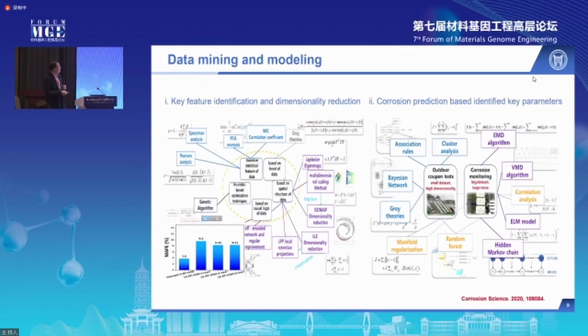And for data mining and modeling, because corrosion is a complex term and it's affected by a lot of different factors, we believe that corrosion data is of high dimensionality. So we applied a two-step approach for data analysis. The first step is to identify the most important parameters that influence corrosion based on either correlational analysis or causality analysis. Once we have the most important factors affecting corrosion, we then use some input and corrosion rates or corrosion current as the output to use machine learning for corrosion prediction.